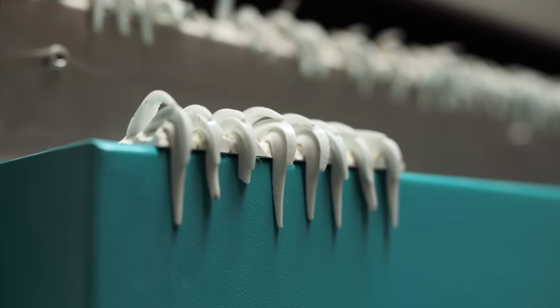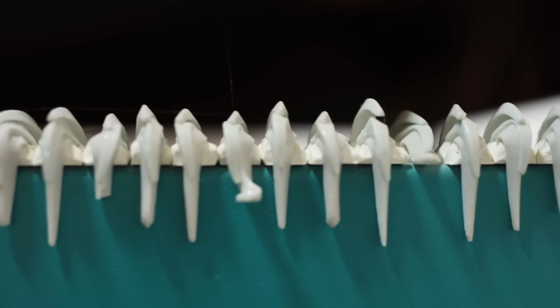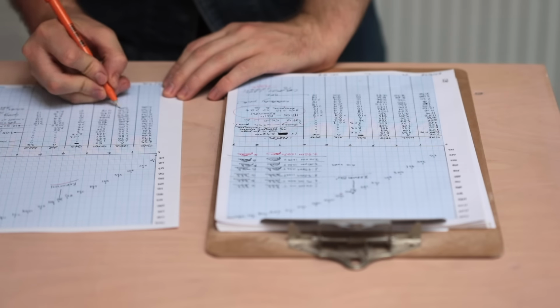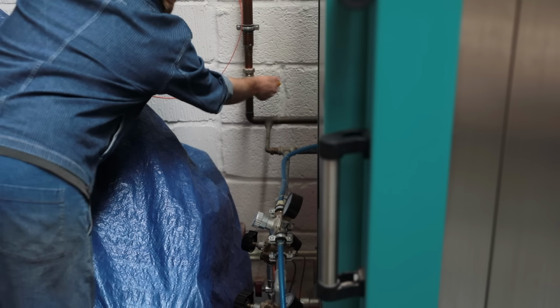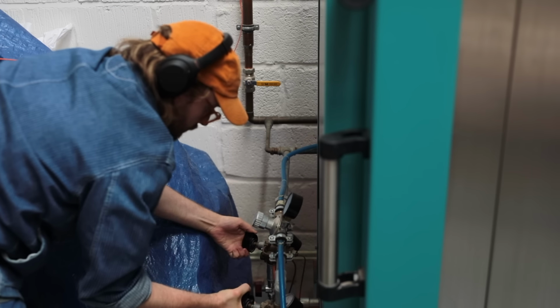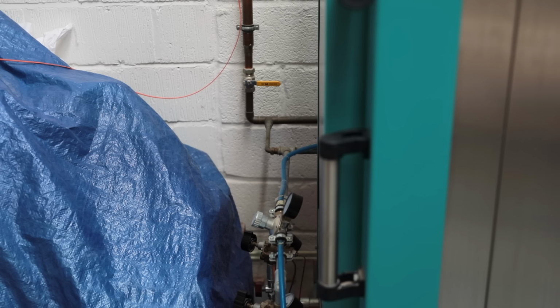It's one of those processes that sounds scarier and more complicated than it really is. These days I can fire it practically without thinking. I simply follow old, successful firing charts, replicating the rise in temperature and initiating reduction at the right point. When cone 10 has bent over at approximately 1290 degrees Celsius, the kiln can be switched off, the firing finally finished.